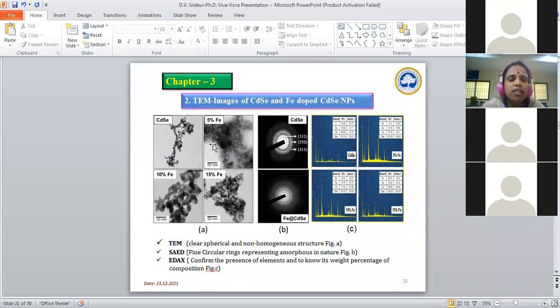This slide shows the images of cadmium selenide and Fe-doped cadmium selenide nanoparticles. Figure A shows transmission electron microscopy images. It shows clear spherical and non-homogeneous structure. Figure B shows SAED, that is, the selected area electron diffraction pattern, with fine circular rings representing that all the synthesized nanoparticles are amorphous in nature, which is in good agreement with the powder XRD data. Then figure C shows a TEM EDAX analysis, which confirms the presence of elements such as cadmium, selenium, and iron, and gives the weight percentage of its composition.